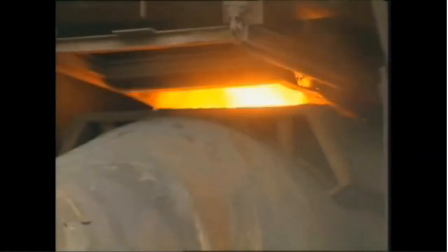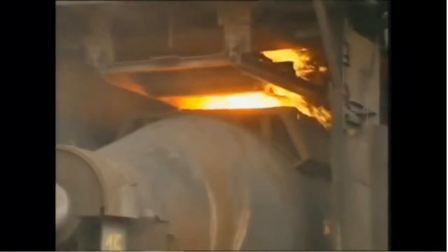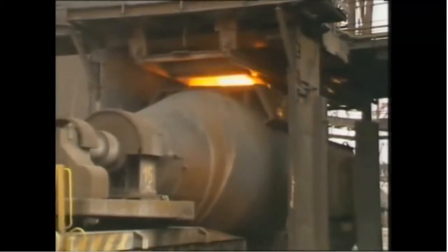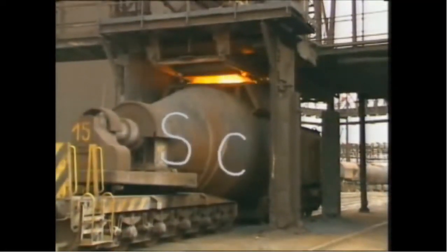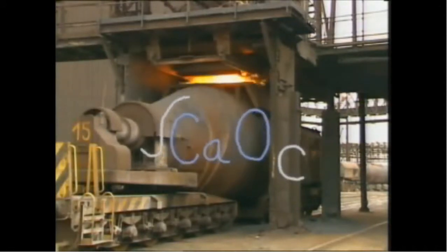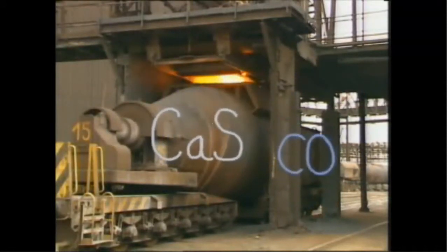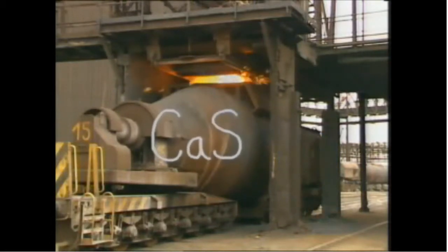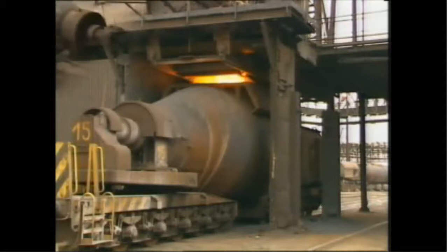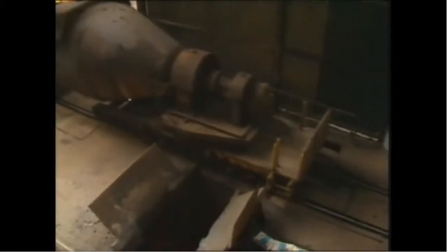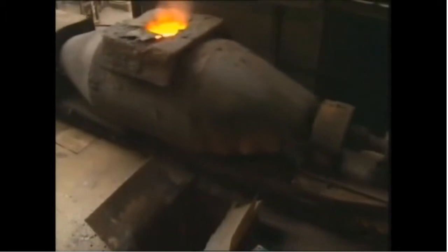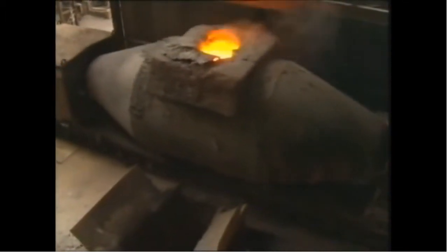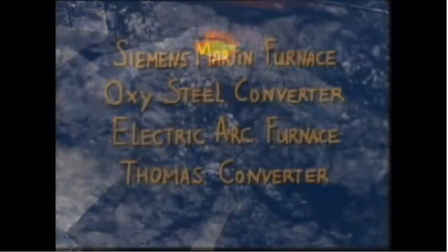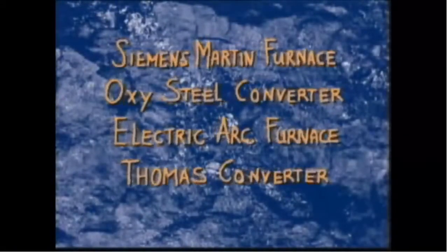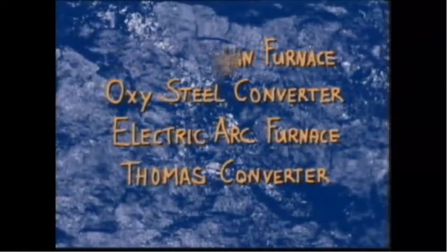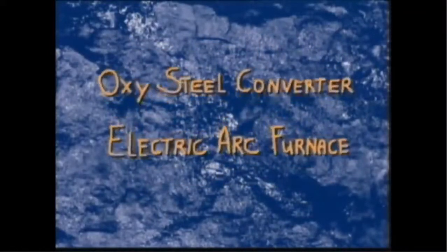It's here that the real steelmaking process starts, beginning with a desulfurization process by injecting lime powder. To avoid loss of ductility at high temperature, a sulfur reduction to values lower than 0.010% is necessary. Now the liquid pig iron is transported to the steel plant. Steelmaking can be carried out in several processes. Nowadays, only the oxy-steel and electric arc processes are relevant.